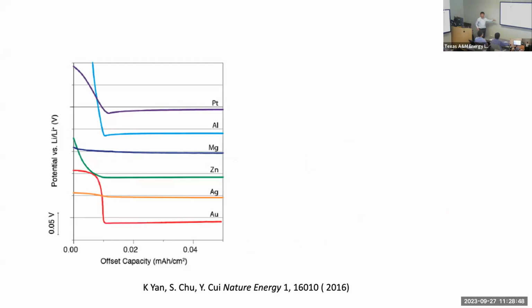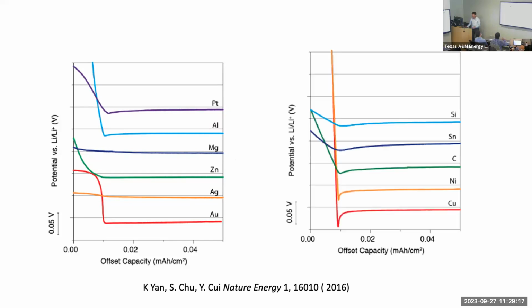Not only that, we also discovered based on the phase diagram, not only gold, we shift the voltage curve up, right? Silver is good, zinc is good, magnesium is good to help lithium plating without overpotential. Actually, after this publication, Samsung borrowed this type of idea for the solid state battery. They put silver on. They published that famous paper several years ago for solid state batteries using silver to guide the uniform plating of metallic lithium. But you look at copper, there's overpotential, and nickel and carbon also have some overpotential right there.